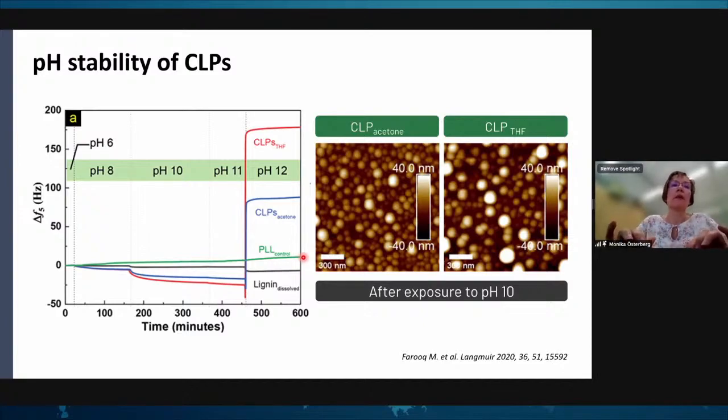are affecting. So if we start from pH 6, we see almost no change at pH 8. So there's very little swelling of these particles. This is quite different from nanocellulose, for example, which swells a lot with changes in pH. So these particles are quite rigid. And the only thing we are seeing is that we have some